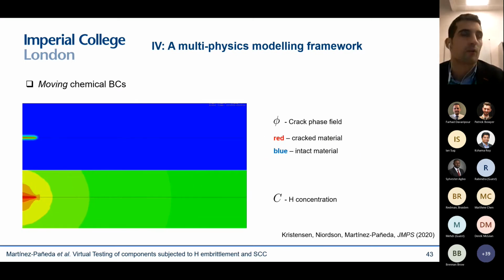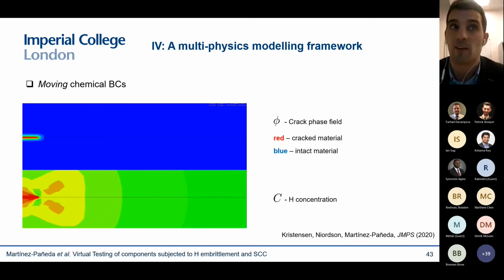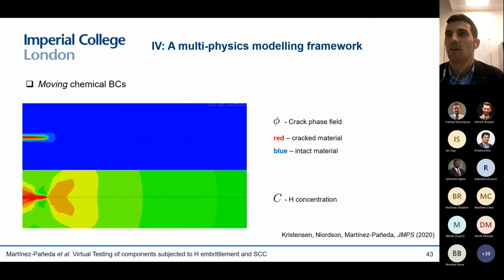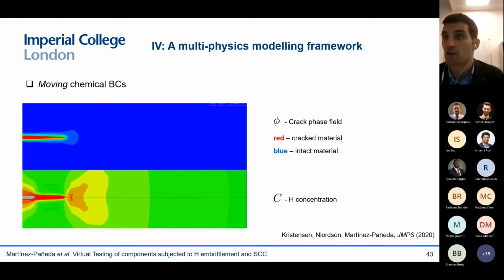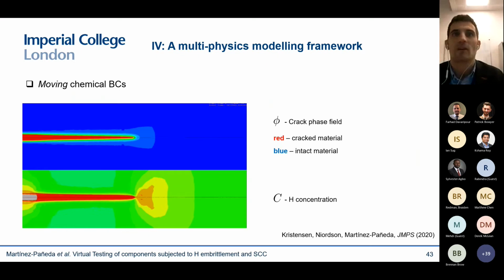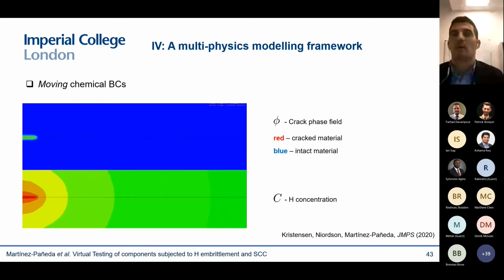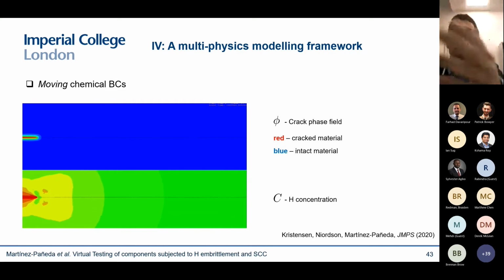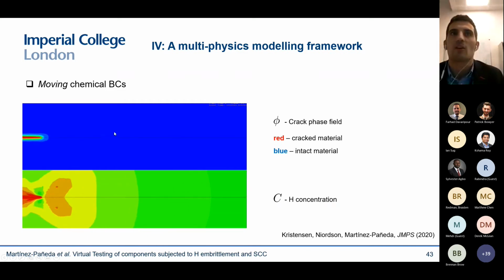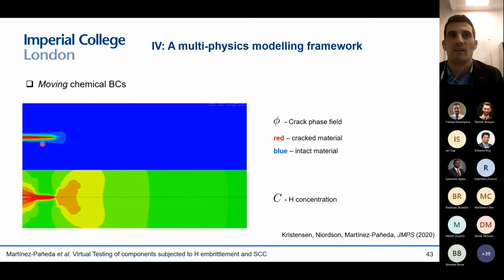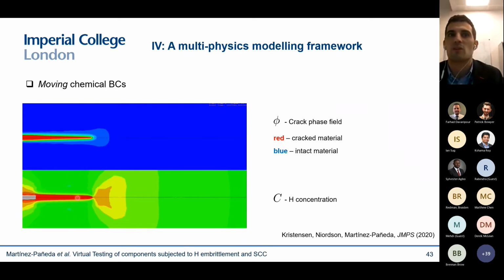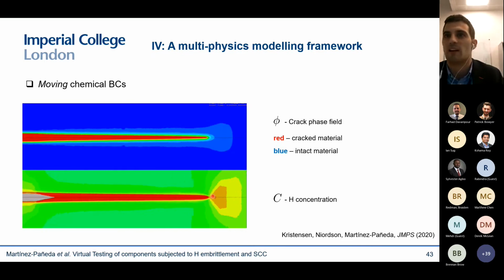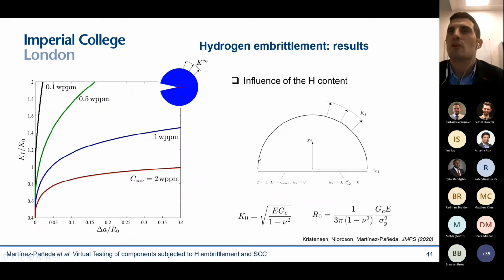Before I show you some results, one last thing that I want to say is that we're also interested in what happens once the crack has initiated. So whenever we have a sample exposed to a hydrogen environment, for example, hydrogen gas or an aqueous electrolyte, as you can imagine, the moment the crack propagates, that environment is going to follow immediately. So the seawater will immediately occupy the newly created crack surface. So we need to be able to capture that, and we do that with a penalty approach. You can see here how the crack propagates and how the hydrogen concentration is following, and also accumulating here where the hydrostatic stress is high. So let me show you some representative examples to show you what we can do with these tools.